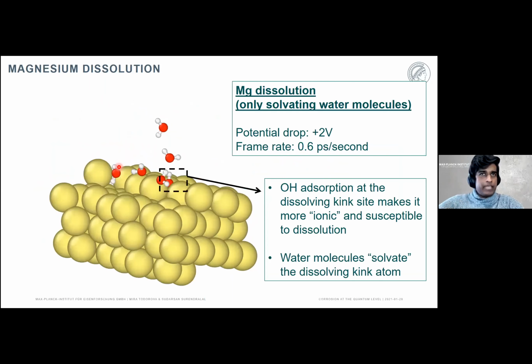I'm about to show you the same movie once more, but what I've done now, I've removed all the molecules that actually don't participate in the dissolution process. So just to give a clear picture of what actually goes on. What you can actually see is even before the dissolution reaction starts, you have an OH ion that is adsorbed on the surface of the magnesium, on the kink site. What this OH adsorption does is that it makes the kink site slightly positively charged.